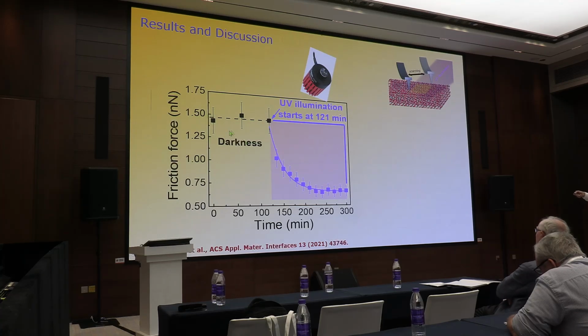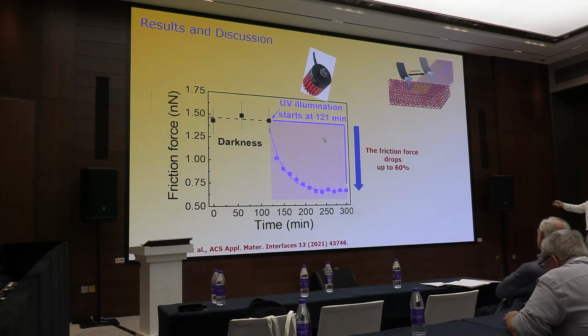At the beginning, in the darkness, the friction force is constant, but when we start the illumination with UV, the reduction is apparent. You can see that we have a reduction in friction force. The reduction is expressive, up to 60%. It's an impressive reduction. And also, you can see that we need several minutes to see the effect. It's not instantaneous. It's another point.